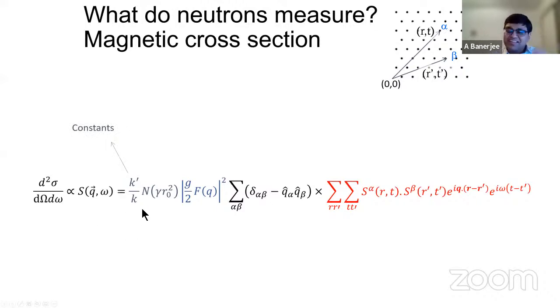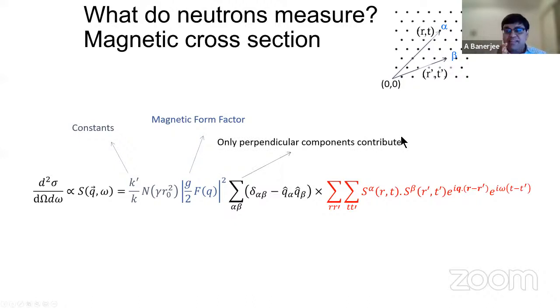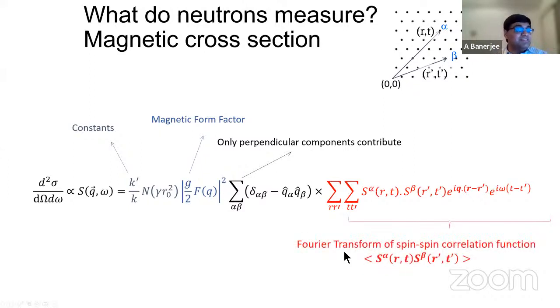In the beginning are some boring constants. It just comes from the interaction term of the neutrons with the spins. Then there is the magnetic form factor. And as I mentioned, this magnetic form factor is what really allows you to separate a magnetic scattering from a non-magnetic scattering. The third term is basically a selection rule, which says that only perpendicular components of the spin scatter. And this is a very important term because it allows you to figure out from the scattering phenomena what directions the spins are pointing in your material and what directions your spins are fluctuating in your material. But the most important term is the Fourier transform of the spin-spin correlation function, which is what we get from the experiments that we do.